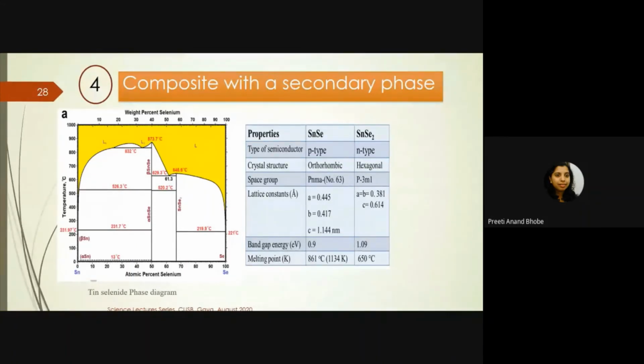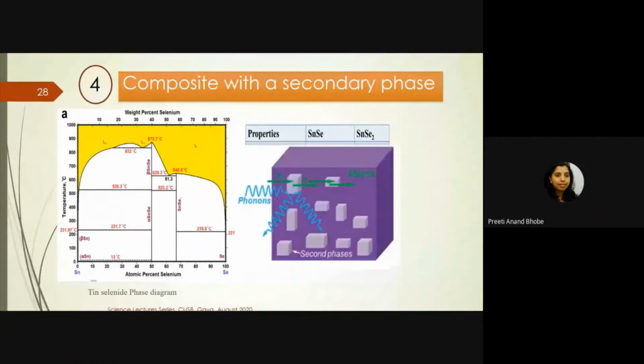compared to pure SnSe. So the idea is that if you take a big matrix of SnSe and try to have some regions which are SnSe2 rich, then the phonons that are propagated would get scattered at these secondary phases, whereas the electronic conduction should not have so much problem, because the SnSe and SnSe2 electronic bands are not that much different. So I should have a smooth conduction for electrons, but I should have scattering of the phonons. This is the idea, and we tried to explore this idea.